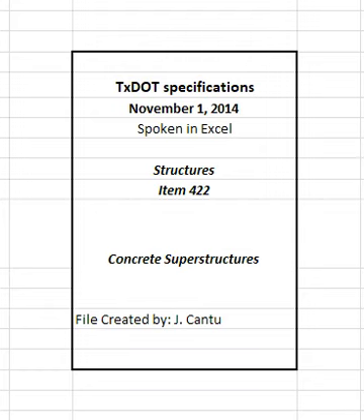4.7.2 Interim curing. Apply interim curing using one of the following options after applying the evaporation protection, if needed. 4.7.2.1 Membrane cure. Apply membrane interim curing at a rate of approximately 180 square feet per gallon. Apply before the water sheen disappears, but do not place over standing water. Fog as necessary to maintain the wet sheen. Do not spray membrane curing on a dry surface.